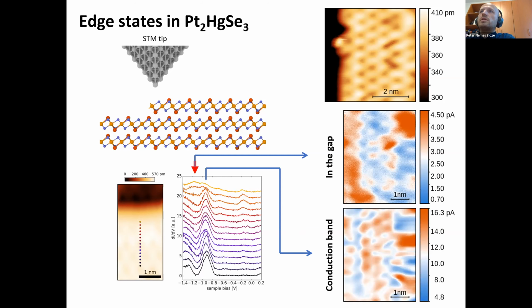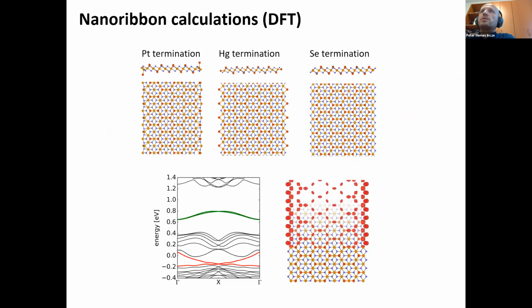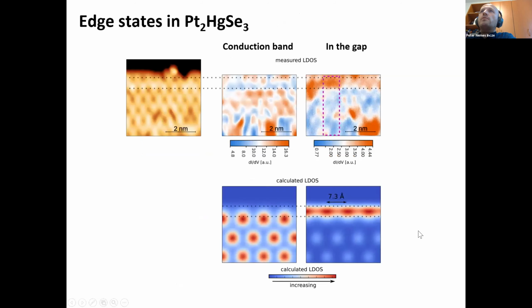Now we tried to reproduce this using DFT calculations, and maybe I'll skip some details of the DFT. We have been able to identify that in our experiments we most probably have a selenium terminated edge, and calculations for this selenium terminated edge show here your topological edge states for this nanoribbon geometry, which are shown in red here. And now if you do a calculated density of states for this edge in the conduction band on the left and in the topological gap on the right, you can see that it fits quite nicely to the experiment.